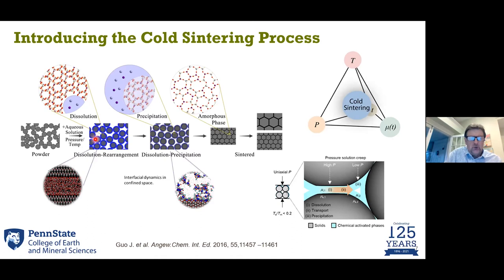that liquid touches the surfaces of these powders, it drives a dissolution process. The same way as sugar is dissolved into your warm cup of tea this evening. And then as you then evaporate that off by a heat treatment, driving it towards the evaporation of water, say 100 degrees, then that sugar then supersaturates and then reprecipitates. In this case, you're driving the surface into a solution in the liquid, and then you're basically supersaturating it and it's reprecipitating. And the dynamics and transport of all those processes then allows this to then densify at temperatures previously unrealized, like 150 degrees Celsius and